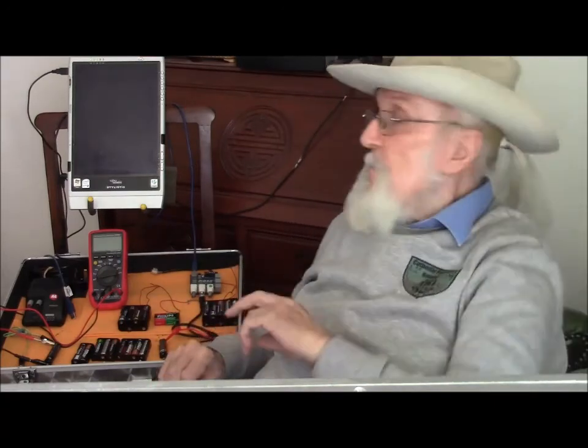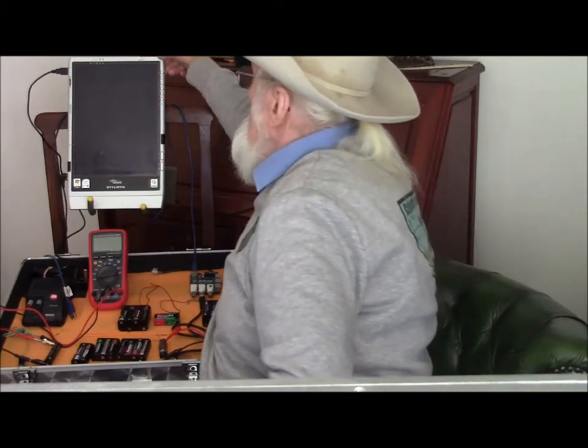To be effective, cathodic protection must reduce the metal potential at each single interface to below its corrosion potential. This is not too difficult to achieve, as each interface is part of the same structure which has a very low electrical resistance. The difficulty is knowing when all the interfaces have been reduced to below their corrosion potential in relation to the electrolyte in their reaction vicinity. Now, I have modelled this situation using batteries,